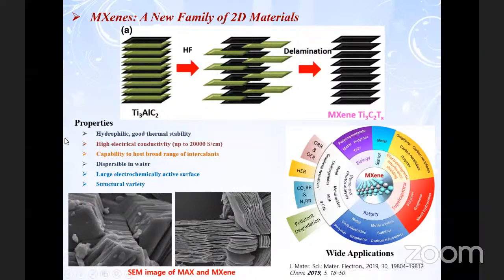Why are the MXenes good? They have wide application in each and every field, similar to graphene. The MXenes are hydrophilic, with thermal stability, high electrical conductivity, and they can host many different materials. They are dispersible in water and aqueous media, with a large electrochemical active surface area and structural variability. You can easily functionalize the surface. For example, titanium carbide: if you remove the aluminum from there, you get this kind of layer structure of MXene.